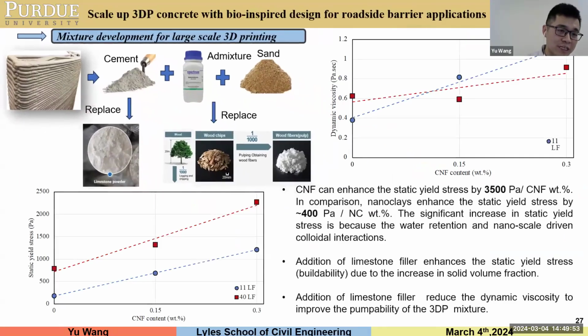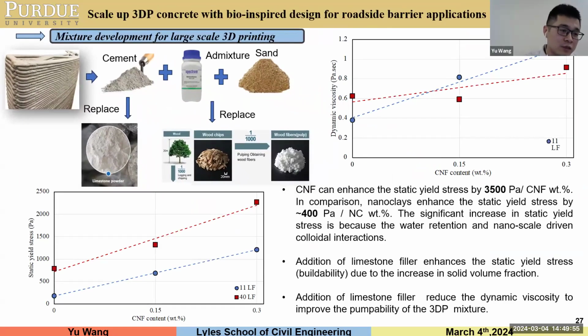So we ran some rheology testing, which shows that the cellulose nanofiber can be a really effective viscosity modifier, increasing the static yield stress and viscosity. It can increase the static yield stress by 3,500 Pascal per percent weight of CNF. In comparison, nanoclay is another studied admixture in the 3D printing concrete field. It can only increase 400 Pascal per percent weight of nanoclay. Adding limestone filler can also enhance the static yield stress, which really helps the buildability of the 3D printing concrete and reduces the cost in the meantime.